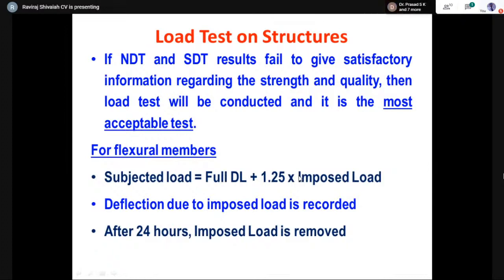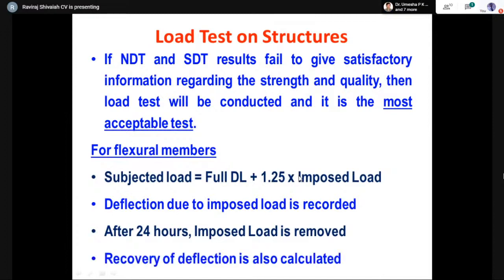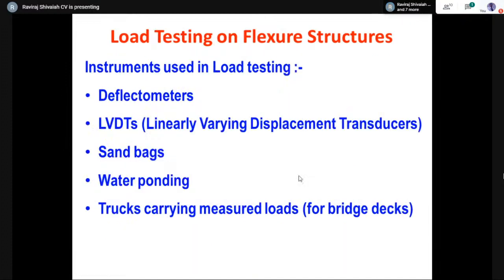And then we try to subject it to increase this load gradually over a period of 24 hours, because we don't want to take any risk of trying to damage the structure. We try to monitor the deflections periodically or continuously. If the deflections exceed permissible values, we stop the test. If the deflections do not exceed the permissible values, we load it to the full extent. Then we wait for 24 hours and then remove the load. We talk about the recovery, and then we can certify the structure is fit to carry the load. So these are some of the things that are normally used to do the testing.